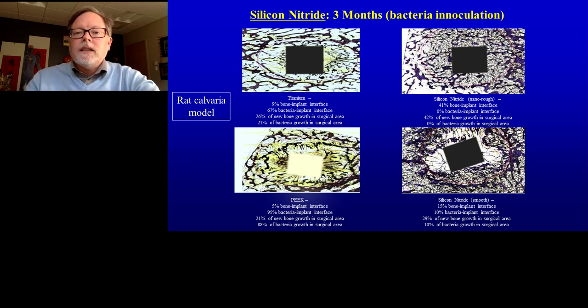So the bacteria that we initially seeded grew very fast. They produced a lot of infection. That infection kept bone from growing, as you might imagine. In fact, if you have bacteria in bone, it becomes a really bad clinical situation where you have to remove the implant and you have to drill out the bone that has the bacteria, because right now there's no way to just kill that bacteria and leave the rest of the bone present. So we quantified this. You can see for PEEK, 95% of the surface was covered with bacteria after 3 months.